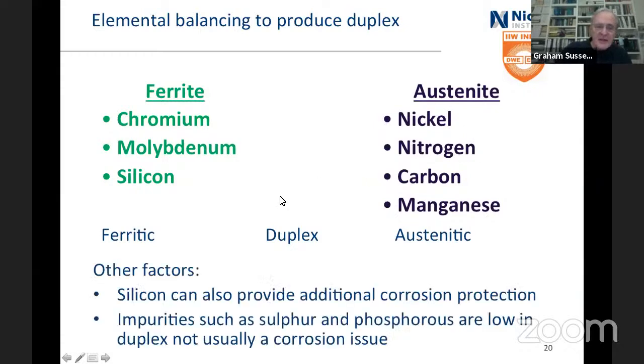Other factors, silicon can also give you additional corrosion protection, but that's nothing to do with the ferrite austenite. That's just to do with a film formed on the surface. And if you remember those 3 high silicon materials on the CPT curve, then that's the reason why they're over there. Impurities such as sulfur and phosphorus are low in the duplex and are not usually a corrosion issue. You don't add, say, sulfur to make a free machining duplex. You do other things.